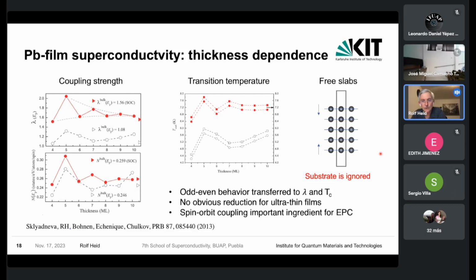We have done this calculation actually without taking into account the substrate. So we have indeed taken just the number of monolayers of lead taken together and built these so-called free slabs where vacuum is on top and on the bottom, and performed all the calculations for these free slabs. And that means that we have essentially completely ignored the substrate. And of course, the substrate will become more and more important the thinner the layers become.